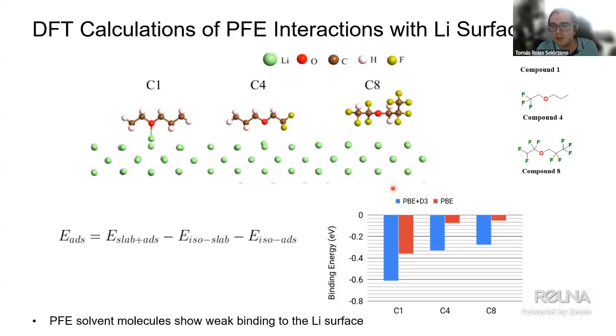Here, the PBE represents one of the most widely used functionals to do the calculations. And PBE-D3 is one of the many ways there are of modeling the van der Waals interaction, which is crucial in this case. We typically model it with and without, to know if there is a significant difference in the behavior after including the van der Waals interaction. Okay, so this tells us that as you increase fluorination, you decrease the level of